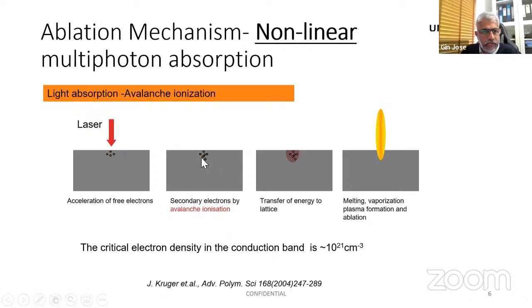So you are effectively exciting the material with a large number of laser pulses that, if you remember the discussion in the morning, create a high, highly oscillatory electric field in the material, which can cause several kinds of after effects within the material. This in turn leads to a very large concentration of electron density in the focused area. When the electron density is of the order of 10 to the power 21 per cubic centimeter, then we believe that the material can effectively ablate on the surface.